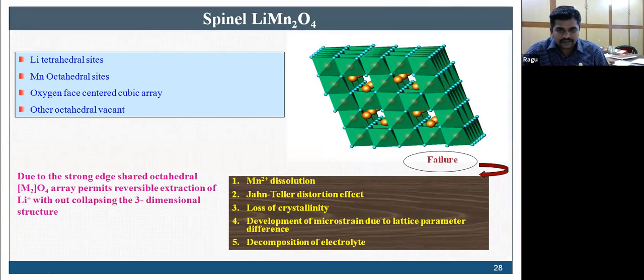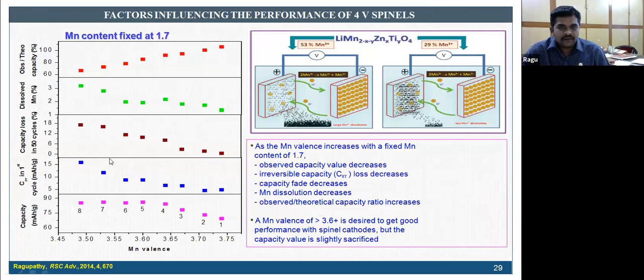So we have addressed how to prevent this manganese dissolution. Don't worry about this graph, capacity, cycle life. The only thing, look at these two different cartoons. On the left hand, you could see 53% of manganese 3 plus. That means you could see a large amount of manganese dissolved in the electrolyte. With the same material, when you have 29% of manganese 3 plus, you could see that only a minimum amount of manganese dissolution is there. Thereby we could control the manganese dissolution by tuning the manganese valence, that is 3 plus.